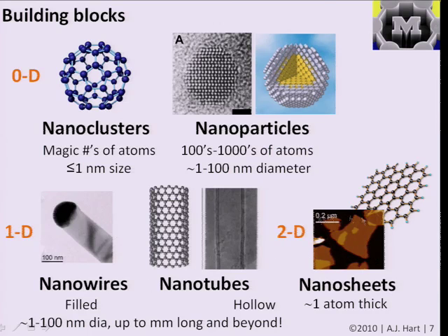Or, in fact, in the growth of sheet-like materials, such as graphene, you have a planar heterogeneous nucleation and growth on a surface. You form a small island, and then that island grows out in a planar fashion, and you end up covering the substrate with layers, and perhaps additional layers are created by nucleating and growing more layers on the surface. So it is like a very controlled monolayer crystal growth in one example of how these two-dimensional sheets are made.